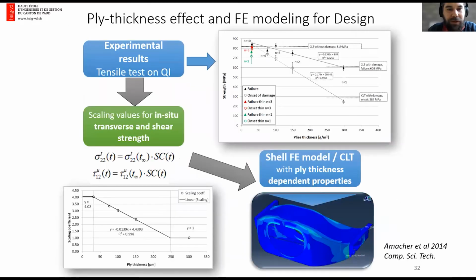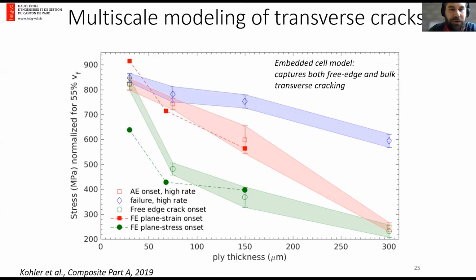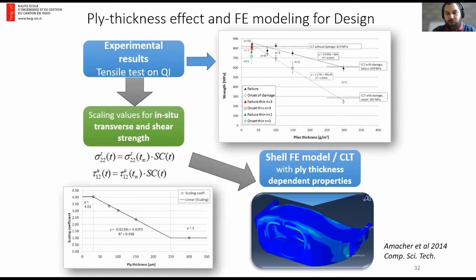And finally, how to model this in terms of design. We cannot use these kinds of models for design. So we used several approaches in the past, but the simplest one is just to use the principle that the transverse strength of a ply in a laminate is a function of the ply thickness. So we just have to calibrate somehow what is the in-situ strength of a ply, either from a test, like we did, for example, a quasi-isotropic test with acoustic emission monitoring. And from this, we can determine what is the effective transverse strength of the ply, or also the in-plane shear strength of the ply as a function of the ply thickness.